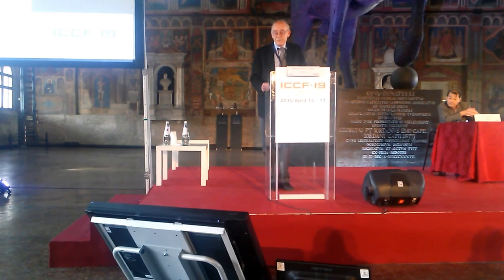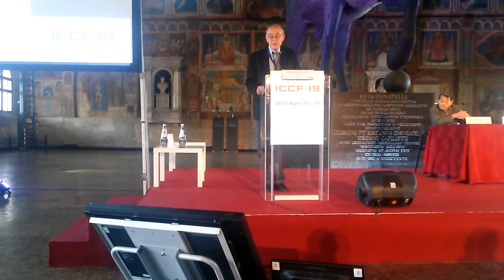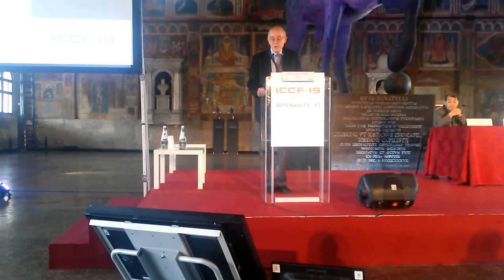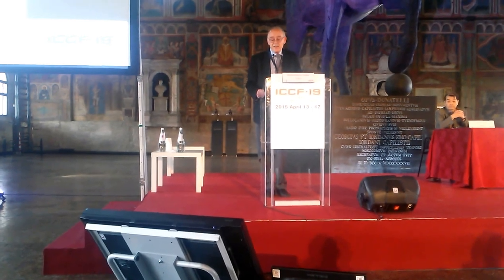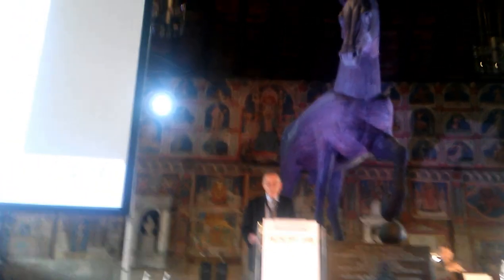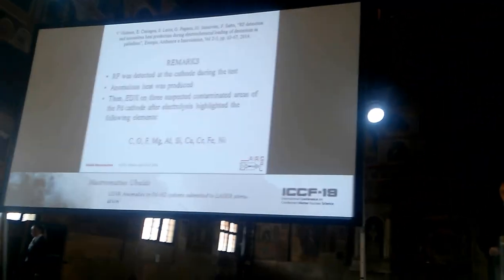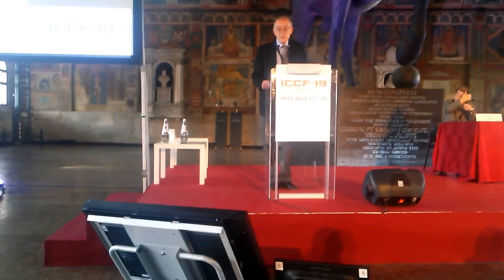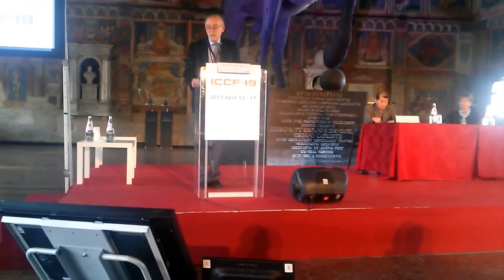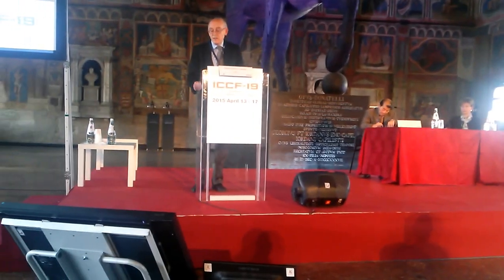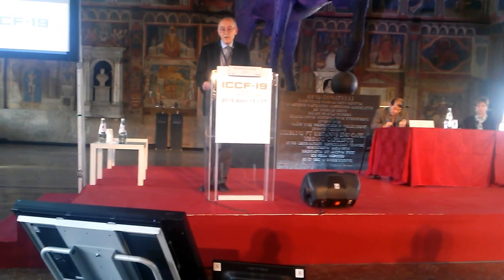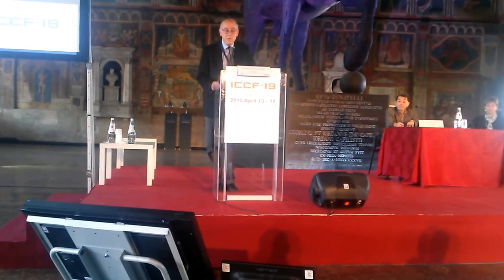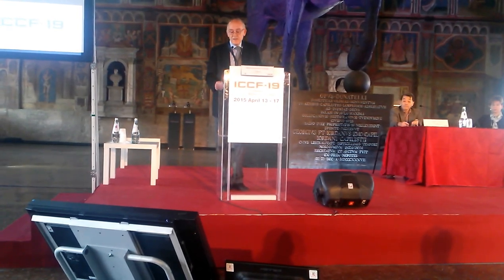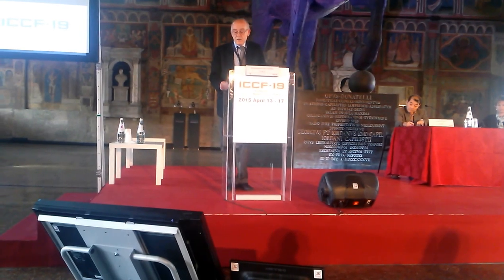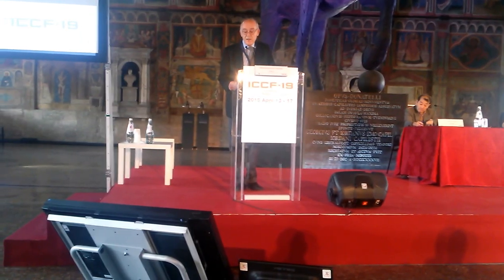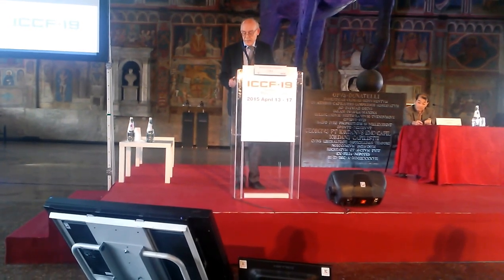And in the case mentioned, they detected an anomalous heat, as was said this morning, and they analyzed three areas of the cathode, and they suspected what they found was coming from contamination. But looking at the list of the elements, I see what I usually find in my experiments with palladium. So I reported the list of these three areas in the EDX analysis. As you can see, again, you have lighter elements with respect to the palladium.